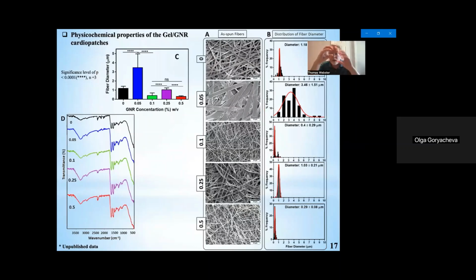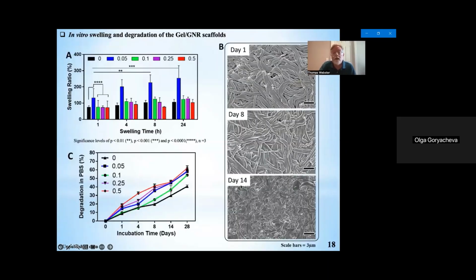Remember, collagen fibers are larger, and then collagen fibrils are smaller, so they have a hierarchical arrangement. But we have pretty good control through this electrospinning process of the size of these fibers, no matter what weight ratio of graphene nanoribbons that we add. So here's a graph showing you some of the various fiber diameters we can get at different graphene nanoribbon concentrations. Here's some FTIR spectra confirming the chemistry, and again some measurements confirming the exact diameter that we get. So pretty good control, narrow distribution of a lot of those diameters.